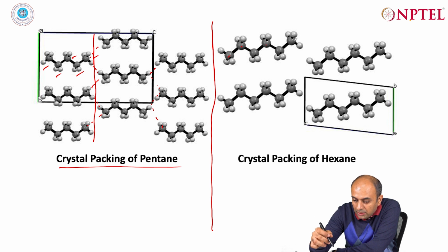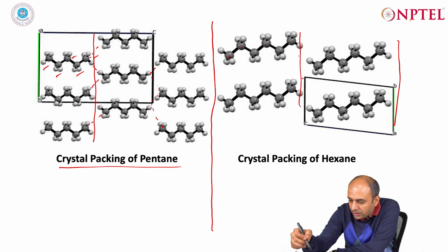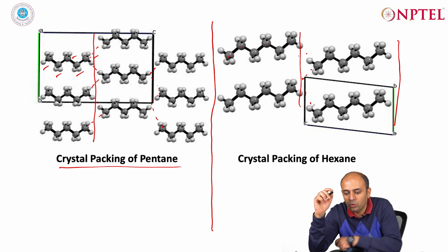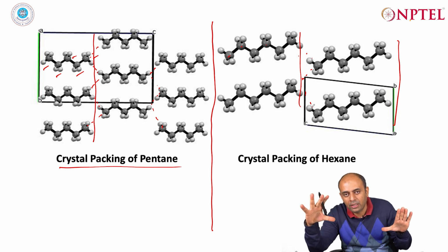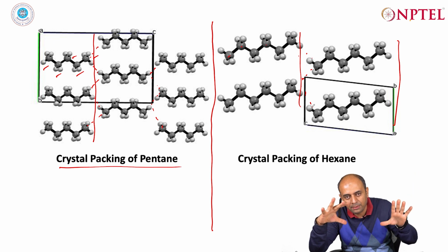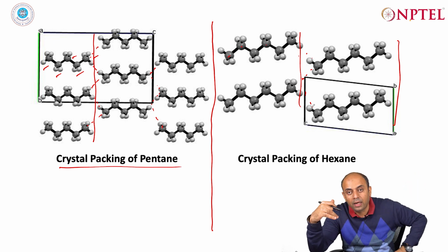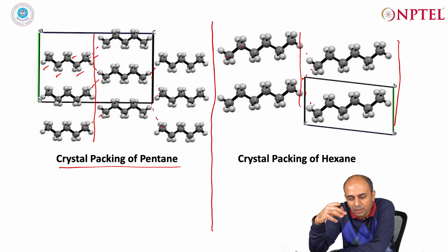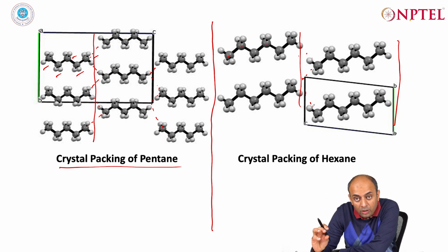And again you can see that there exists a layer of molecules. You see this constitutes one layer, and then this is the next layer of molecules. Again they are slightly displaced so as to maximize the HH contacts. So, you never get to have an opportunity where you have direct face to face interaction, rather they are slightly displaced so that they can minimize the sterics and maximize the electronics, and the subtle interplay of the electronics and the sterics is what governs the close packing of molecules.